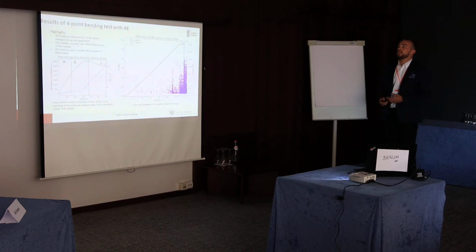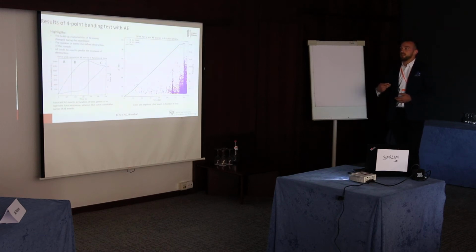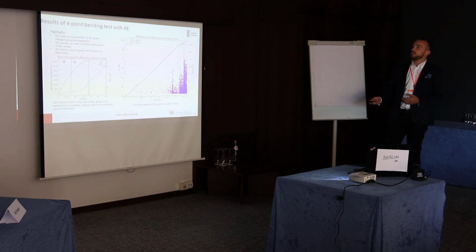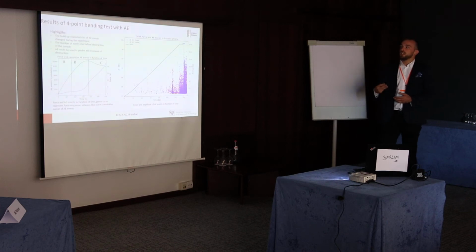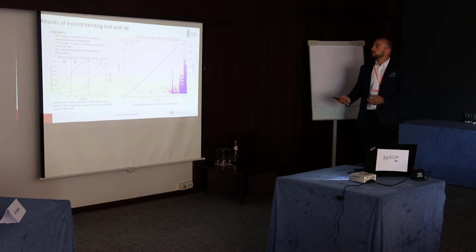In the results from the tests, as you can see, just before breaking, the cumulative number of events rises significantly, and this is much better seen in this picture. In the beginning we have a mostly linear curve, then the nature of the curve changes, and after maximum force we change the nature again. So it could be linear, but we didn't check.